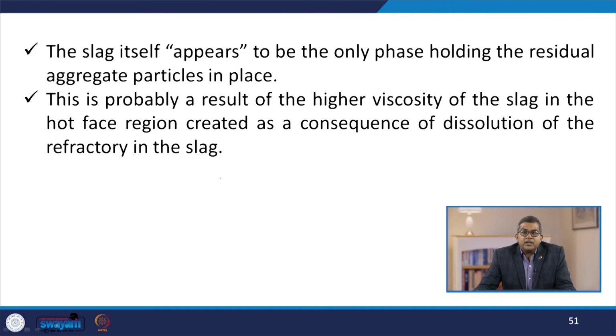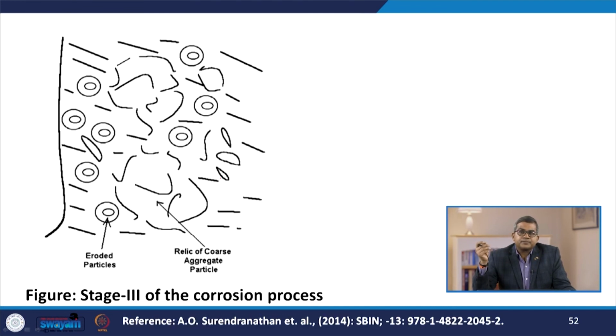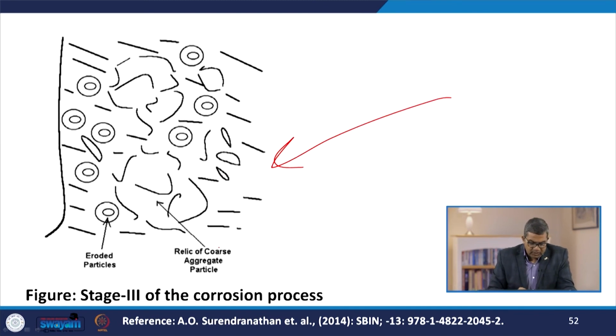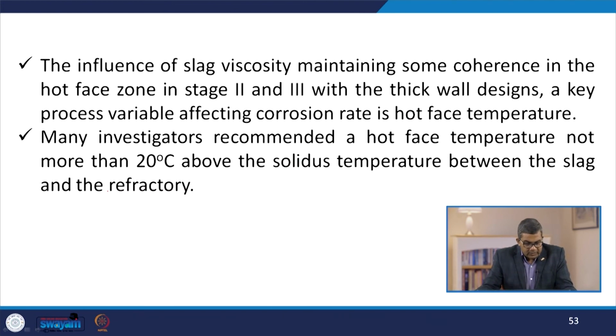The slag itself appears to be the only phase holding the residual aggregate particles in place. This is probably a result of higher viscosity in the slag in the hot face region, created as a consequence of dissolution of the refractory in the slag. Here you see stage 3 of the corrosion process. Here you see the relic coarse aggregate particles, and this one is the eroded particles. Now, the influence of slag viscosity maintains some coherence in the hot face zone in stages 2 and 3.